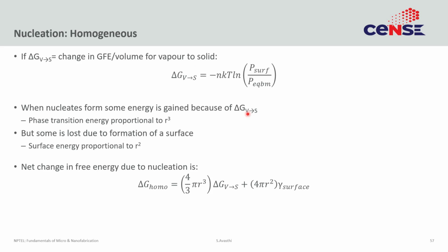Now, this is the nucleation that does not happen on the surface, but rather happens in gas phase. So, this is not what we typically do in CVD, but just bear with me for 1-2 slides, you will see that this is relevant. Now, imagine that you have a container, and in that container you have pushed in a certain precursor, and you have made sure that the pressure of the precursor inside the system is higher than its equilibrium. So, you have made sure that the system is under supersaturation.